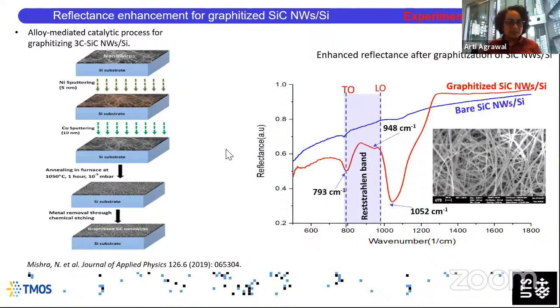Now, what we realized is that experimentally, using the alloy-mediated catalytic process on the silicon carbide nanowires results in a bunch of nanowires that look like a forest, which you can see on the right-hand side of this slide. You can see this very intricate and random structure of coiled nanowires which are lying on each other. So this is quite different from having a nice, smooth, periodic arrangement.